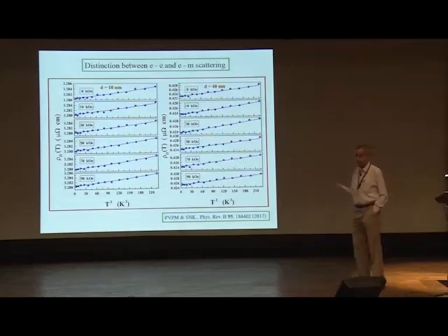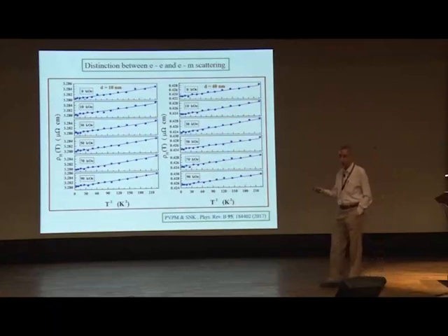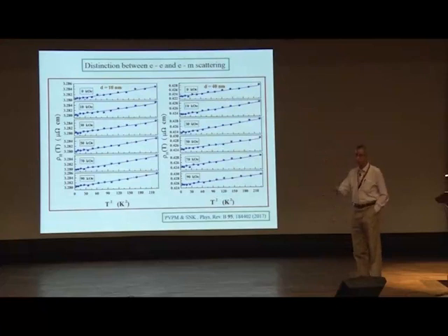And this was seen in not only just iron, cobalt, nickel. It was seen in a large number of alloys, throughout all metallic ferromagnets of all kinds. They saw this T-square dependence and attributed it to just electron-magnon scattering. And we show that that is not true. One has to do this experiment to find out whether that is so or not.